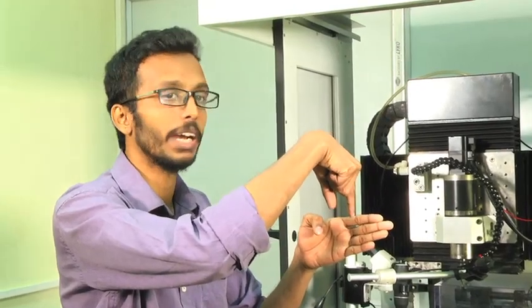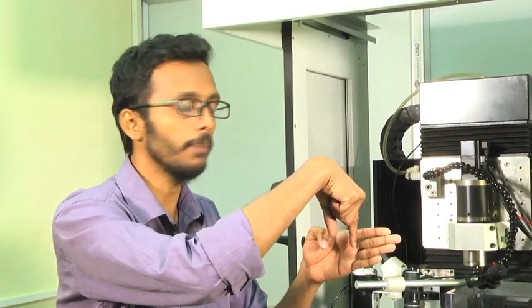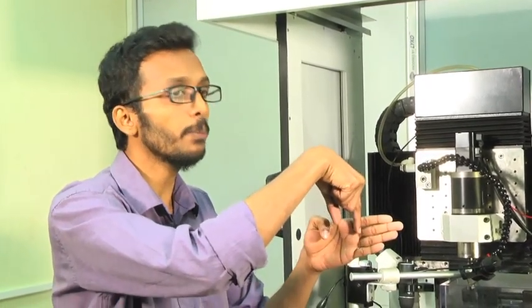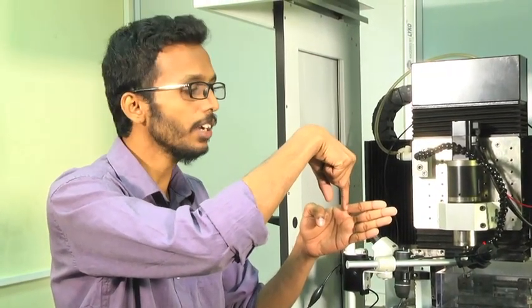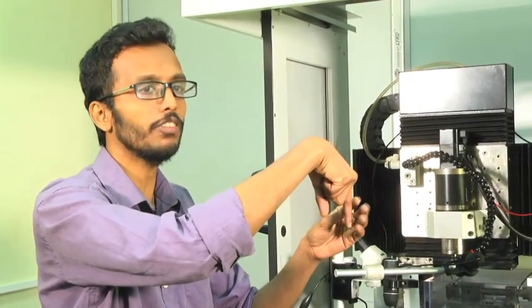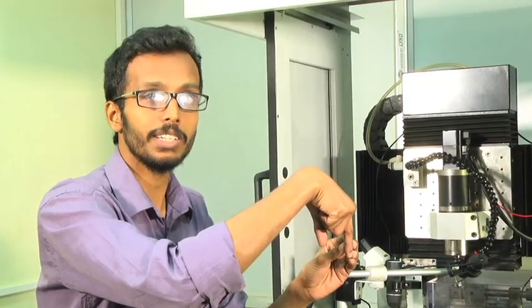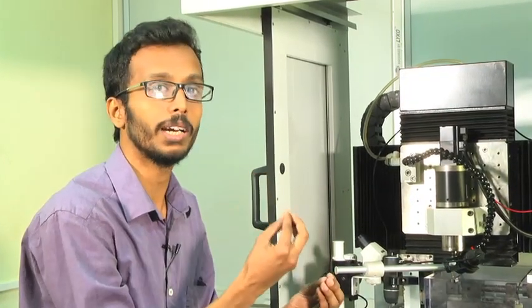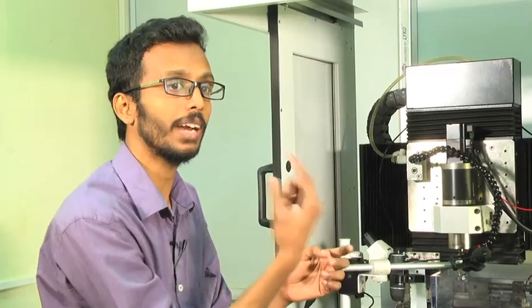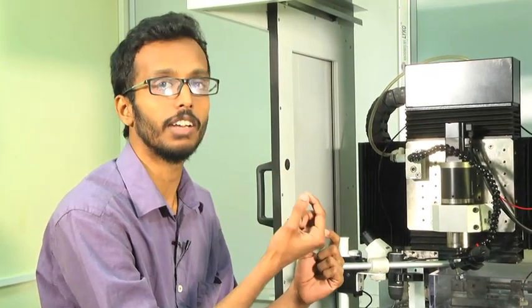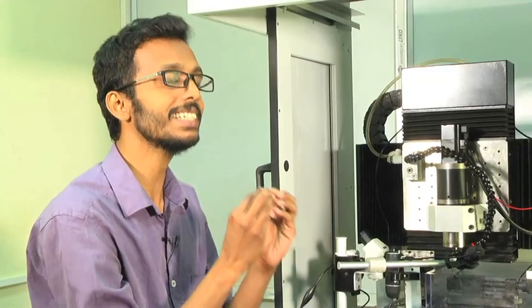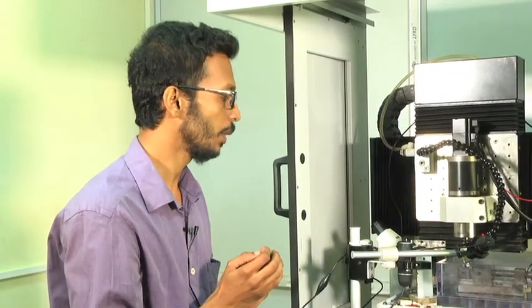After that, to reduce from 0.5 mm to 0.2 mm, we will be moving 150 micron inward, and we will be moving along this direction so that the sparking will occur between the tool and this standard piece, the tungsten carbide block, and the dimension will reduce from 500 micron to 200 micron. Why? It is going inside by 150 micron and it is rotating, so 300 micron will be taken from the outer side, and what will be left is 200 micron diameter. Okay, this is just like a turning process, but there is no cutting tool available; the whole machining is done by the sparks.